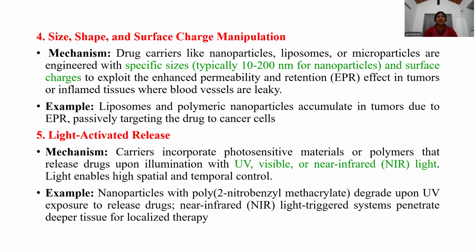Next one is the shape, size, and surface manipulation. So the mechanism involved is that carriers like nanoparticles, liposomes, or microparticles are engineered with specific sizes, typically around 10 to 200 nanometers, and the surface to exploit the enhanced permeability and retention effect in tumors or inflamed tissues where the blood vessels are leaky. Examples include liposomes and polymeric nanoparticles accumulating in tumor due to EPR, passively targeting the drug to cancer cells.